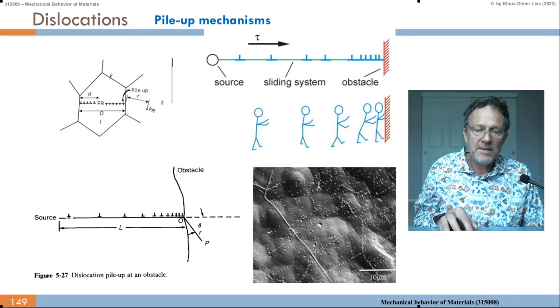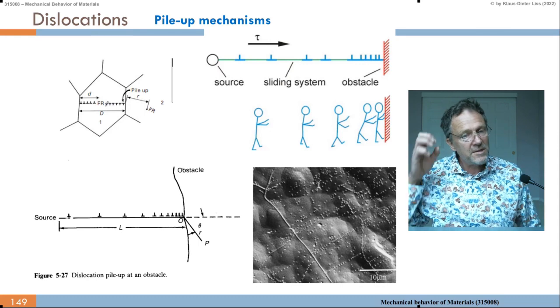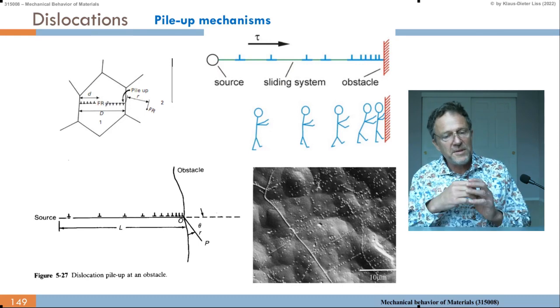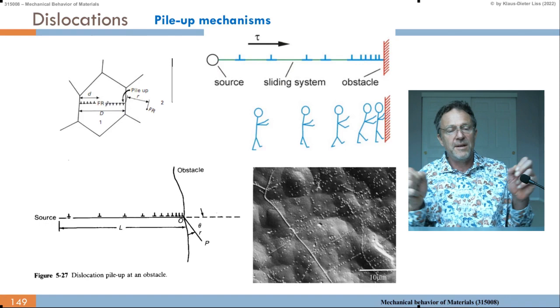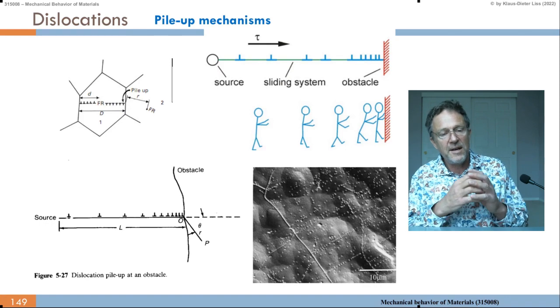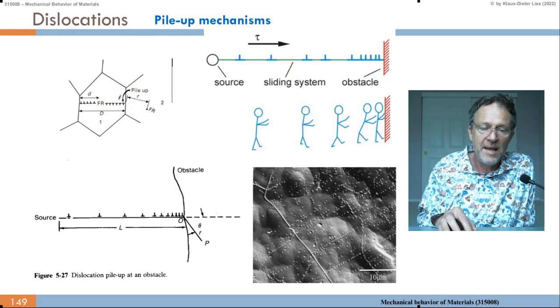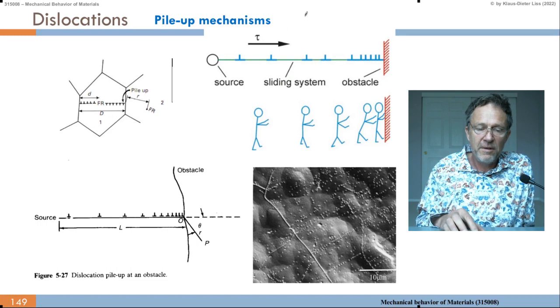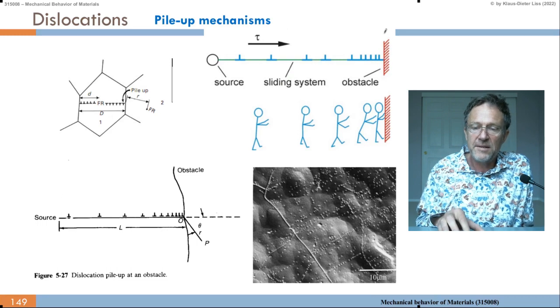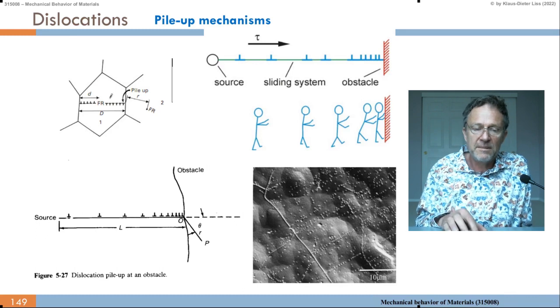So let's say this is a grain, and it has a typical diameter D. And if you put a Frank-Read source here, you know the Frank-Read source, which expels dislocation loops, and these dislocation loops move out, and the next one follows, and the next one follows. How far can they move? The first dislocation can move until it hits the wall, until it hits the grain boundary here. Then the next dislocation comes.